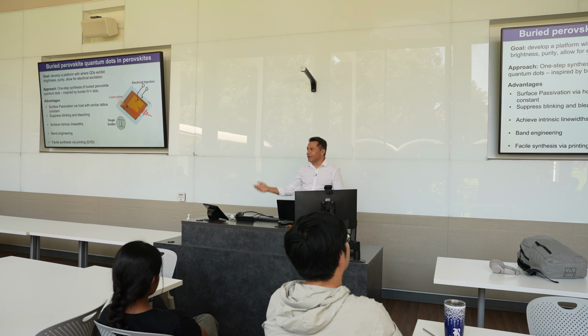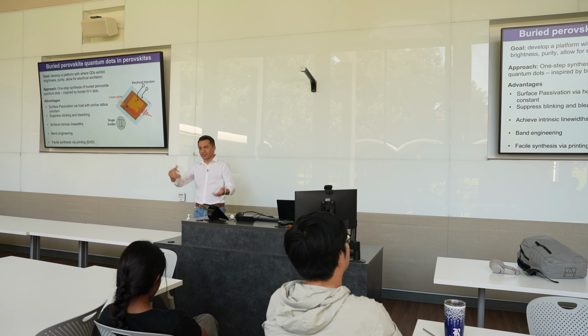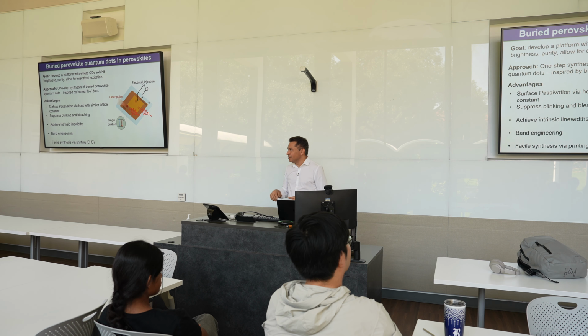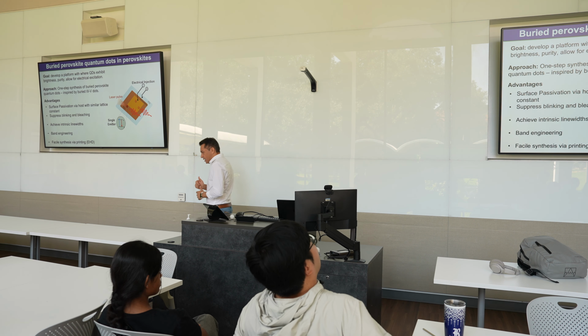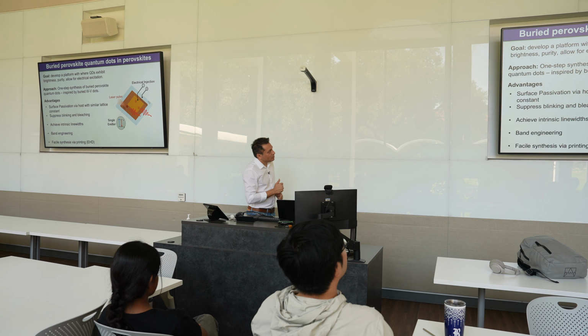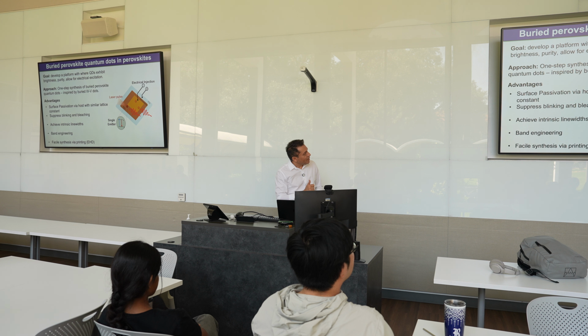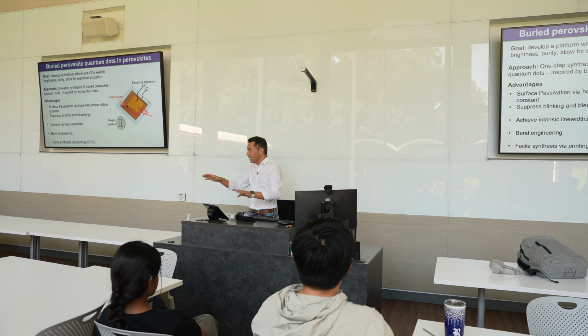We want to suppress this blinking and bleaching, which is a huge issue. This is just changes, your emission is not very stable. And get to intrinsic line widths, essentially determined by Heisenberg's uncertainty principle, ħ/2, you want to get to that type of limit. The intrinsic line width for these systems would be of the order of, I want to say, 100 micro electron volts at low temperature, extremely sharp. That's almost like a molecular system. Molecules have very sharp lines because they have a two-level system, that's all they have.